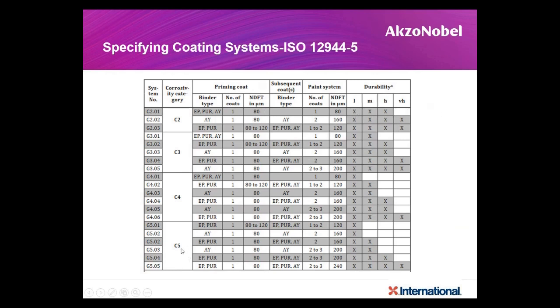For example, for C5, that is marine coastal environment, if you want a durability of very high, greater than 25 years, you should have this coating system: an epoxy primer or a polyurethane primer of 80 microns, subsequent coats of epoxy, polyurethane or an acrylic, leading to 240 microns.